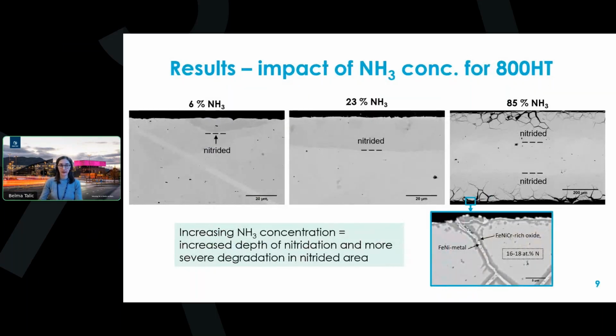We also looked at the cross sections of the alloy coupons after the exposure, here illustrated for alloy 800 HT. Where we also can see that at 550 degrees, increasing ammonia from 6 to 23 to 85%, both the depth of nitridation increases, but also the amount of nitrogen dissolved in the nitrided area. So in the SEM images, you can very clearly see a contrast difference from the near surface area, which is darker, to the base alloy. So this darker area is where we, by EDS, also detect nitrogen dissolved in the alloy.